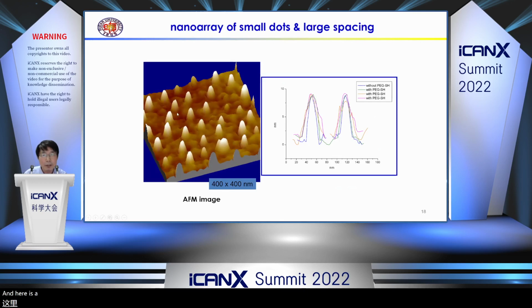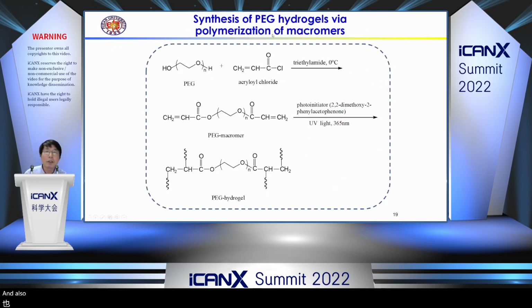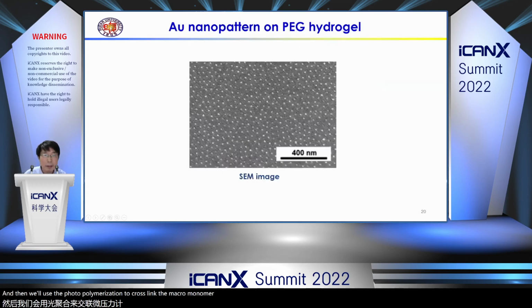And here is a characterization by AFM. You can see from the height scale of the AFM that the size of the gold dot is a bit less than 10 nanometers. So it is what we would like to make. And also we synthesize the PEG hydrogel using a technique called PEG macromonomer. Starting from the PEG with two hydroxyl end groups, we use acryloyl chloride to link the double bonds to both ends. And then we use photopolymerization to cross-link the macromonomer to obtain the PEG hydrogel. Here is one of the early images of the gold nanoarray on the PEG hydrogel.